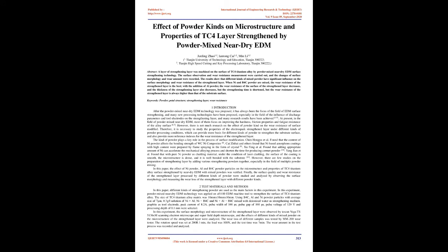When Ni and B4C powder are mixed, the wear resistance of the strengthened layer is the best. With the addition of Al powder, the wear resistance of the surface of the strengthened layer decreases, and the thickness of the strengthening layer also decreases, but the strengthening time is shortened. However, the wear resistance of the strengthened layer is always higher than that of the substrate surface. Keywords: powder, petal structure, strengthening layer, wear resistance.